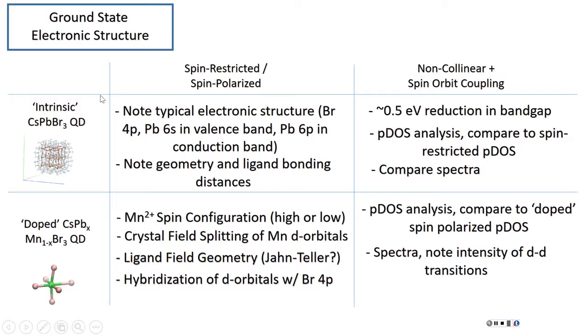And then once we optimize both of them, we do non-collinear plus spin orbit coupling single point calculations to include spin orbit coupling effects, because both lead and manganese have, well, lead has a large spin orbit coupling associated with it. Manganese has a smaller one, but it's still there. So to do accurate modeling of the photophysics, you have to include spin orbit coupling. So that's why we do single points for both of those.